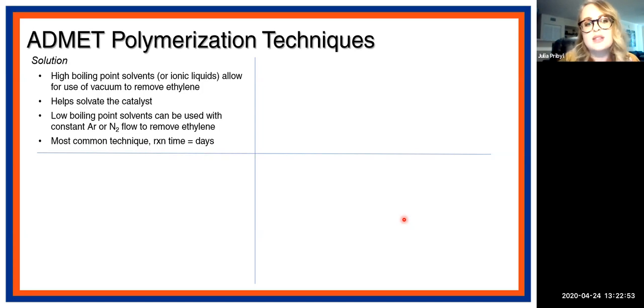And there are some instances where we use low boiling point solvents. And in that case, you can remove the ethylene by having a constant argon or nitrogen flow into the solution. A little bit of a downside of this type of technique is that the reaction time is often on the order of days. So you get very nice results, but it takes a long time to get high molecular weight polymer.